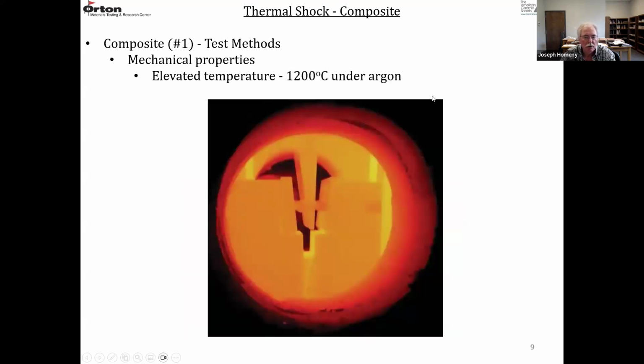And this is just what the sample looks like at high temperatures, looking through one of the windows in the furnace. So it's a circular window. This is 1200 degrees C under argon. So you can see the wedge, the cylinders, the transmission wedges, and then the notch here. You can actually see a crack that's been propagated from this starter notch.